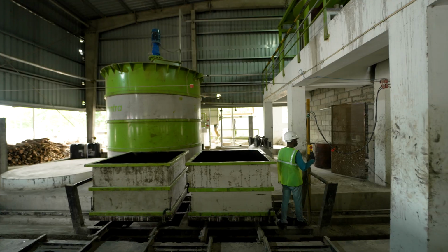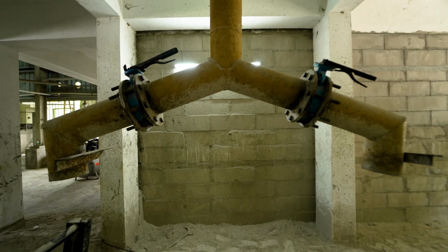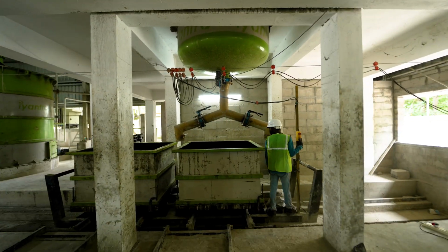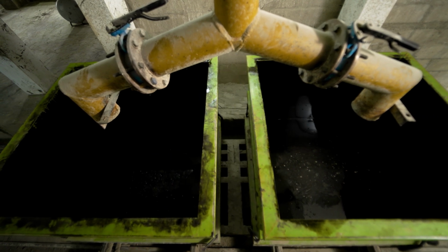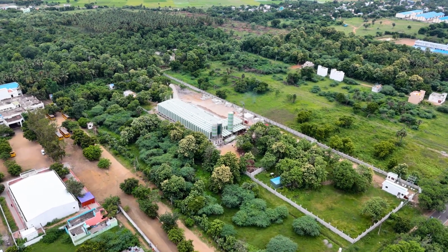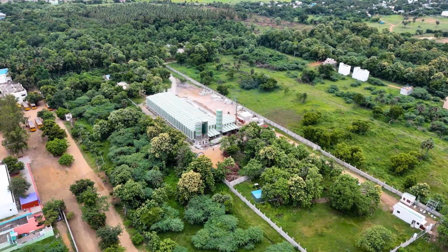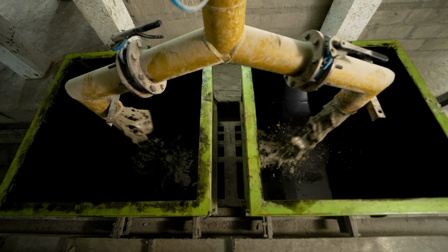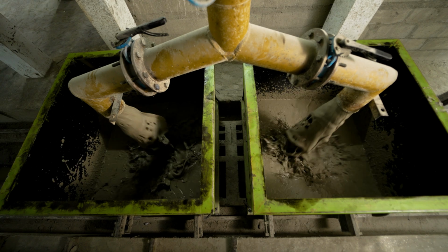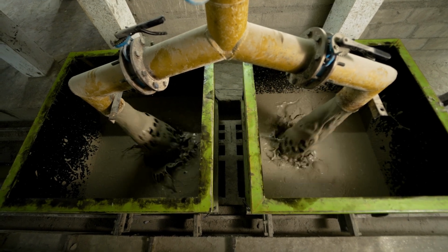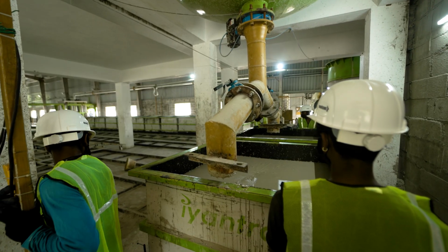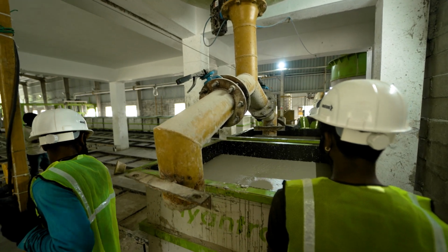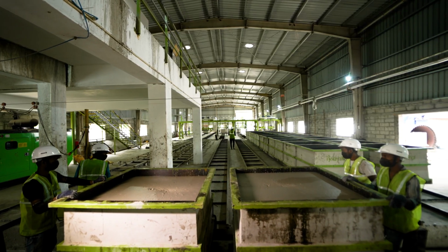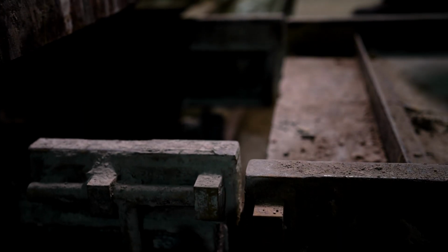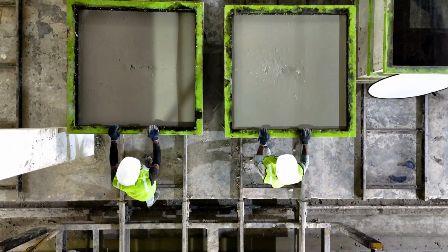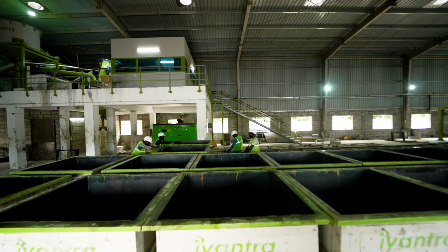Molding. To shape the aerated slurry into blocks, the foamed slurry is poured into metal molds. The molds are typically designed to produce large cakes that are later cut into smaller blocks. The slurry is allowed to expand and fill the mold completely. The molds are left undisturbed for 30 minutes to 2 hours at room temperature to achieve initial setting.